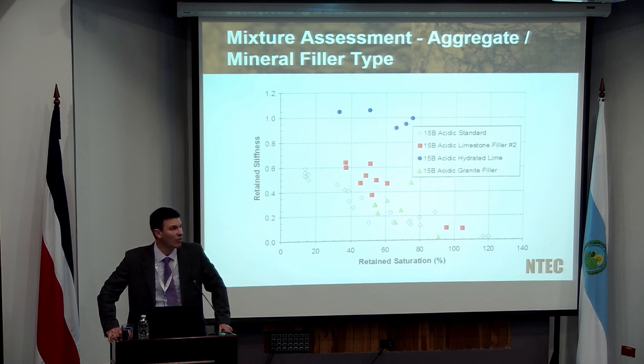However, if we add only about 1% hydrated lime as a replacement filler, in other words, you take out some of the natural filler in that material, so your sub 75 micron material, and replace it with hydrated lime, even down to about 1%, we see a large increase in terms of that retained stiffness. In other words, the material now has the ability to resist that moisture sensitivity. The issue with these tests is that they don't tell you why. They tell you the end result, and they say, yes, if you have designed and incorporated the right type of materials into your particular asphalt mixture, you can improve its performance and resist moisture damage. But it doesn't give you the mechanism in terms of what is actually allowing you to improve that performance.